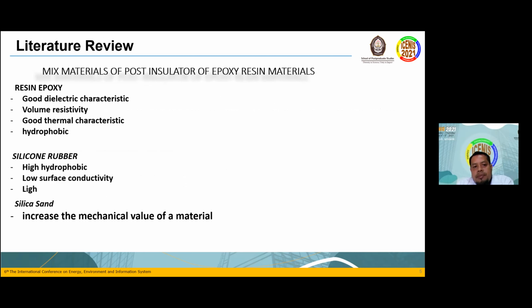The insulator is a mixed material. Both insulators are of epoxy resin material. 1. Epoxy resin, because of good dielectric characteristic, volume resistivity, good thermal characteristic, and hydrophobic. 2. Silicon rubber, because of high hydrophobic and low surface conductivity. And last, silica sand, to increase the mechanical value of the material.